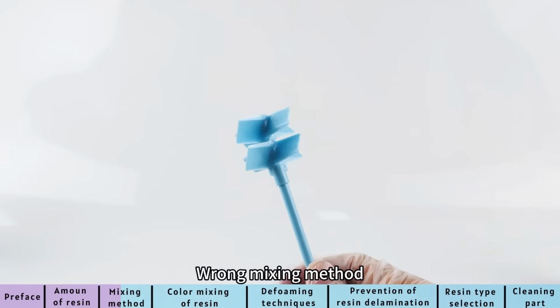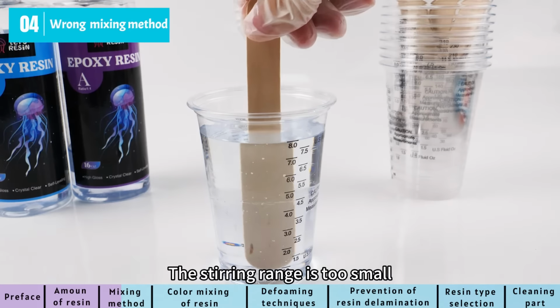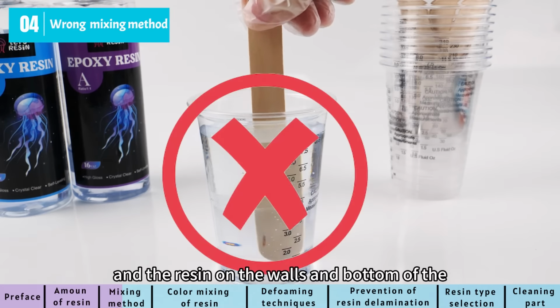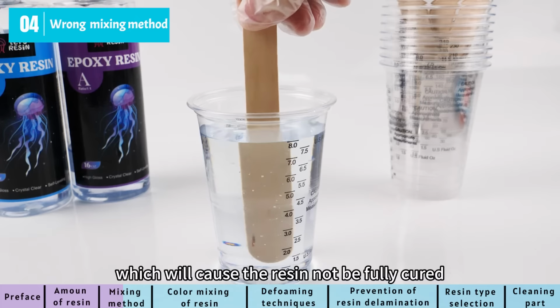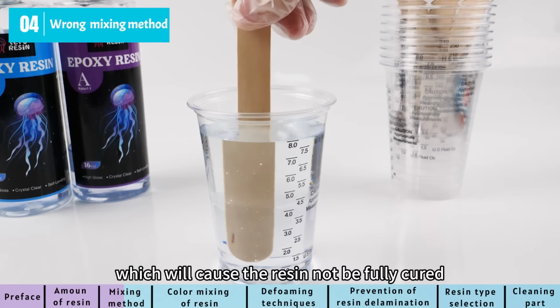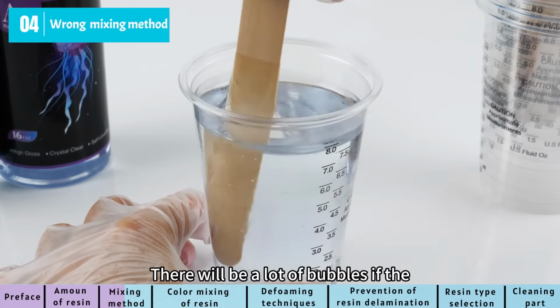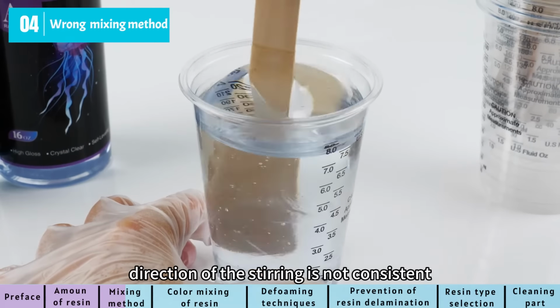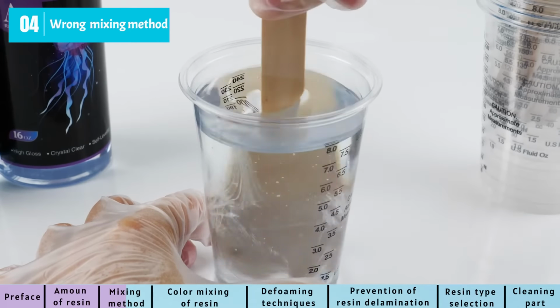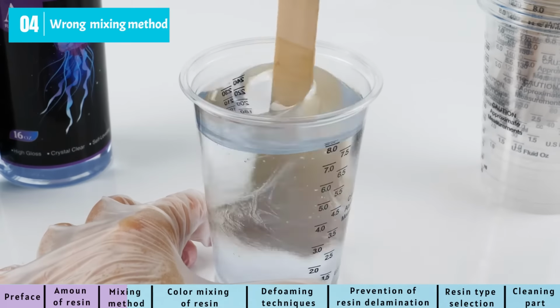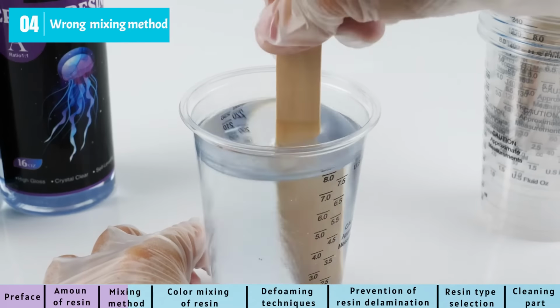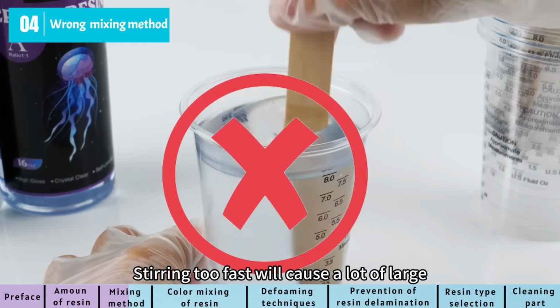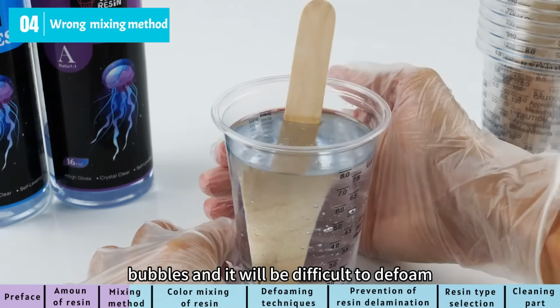Wrong mixing method. The stirring range is too small and the resin on the walls and bottom of the cup are not stirred, which will cause the resin not to be fully cured. There will be a lot of bubbles if the direction of the stirring is not consistent. Stirring too fast will cause a lot of large bubbles and it will be difficult to defoam.